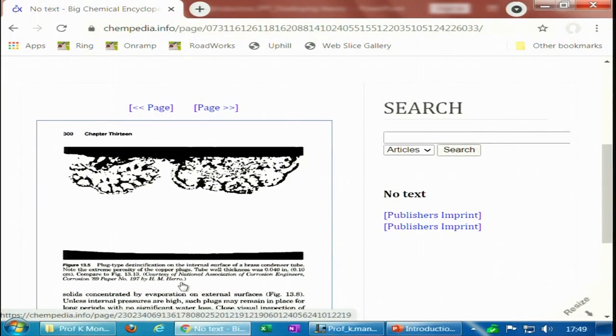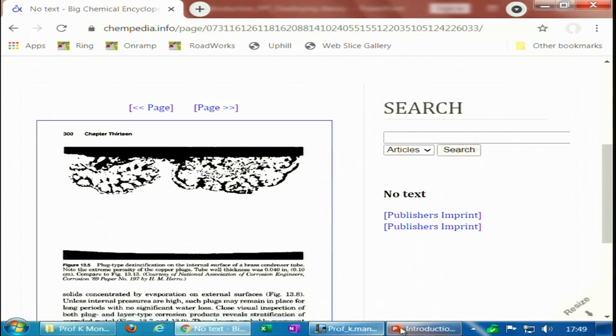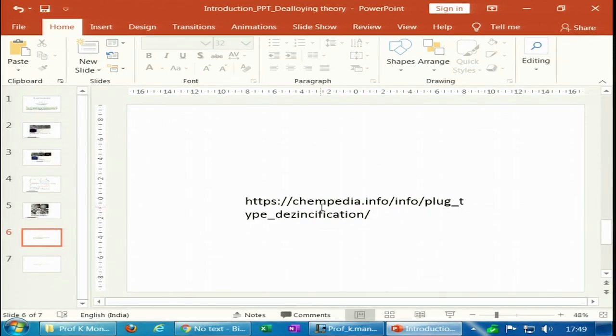Here is a brass condenser tube showing the internal surface — extreme porosity of the copper plug. These are mostly porous copper because zinc has gone out, and that is why they are called copper plugs — it is not uniform, it is localized. This is a plug type example taken from a National Association of Corrosion Engineers paper by H. M. Herro, shown here entirely for educational and teaching purposes.